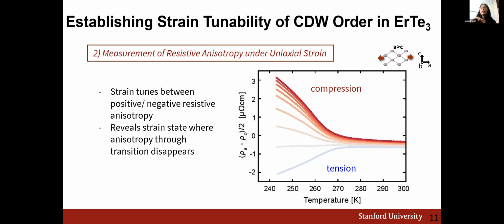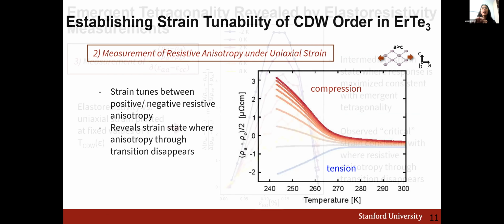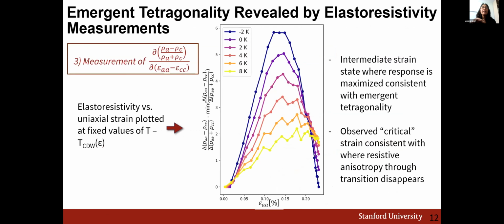And then promisingly, this measurement reveals that there indeed is some intermediate strain state through which, when we cool through the CDW transition, the anisotropy associated with the CDW transition disappears, such that there's an equal amount of CDW order in both directions. And then finally, just showing that elastoresistivity data.